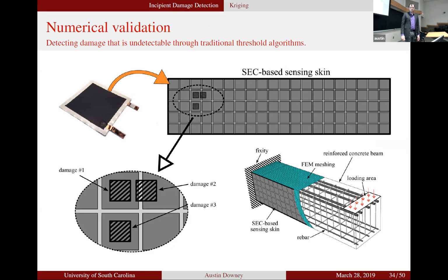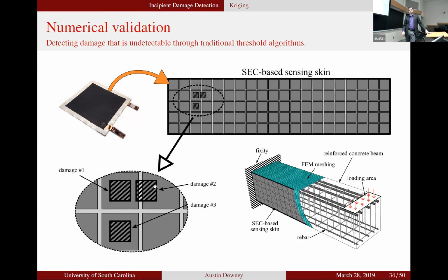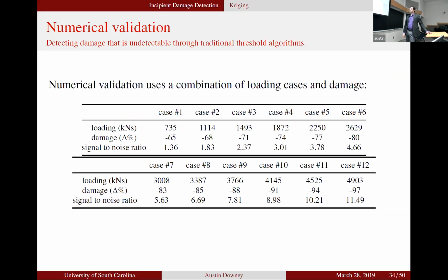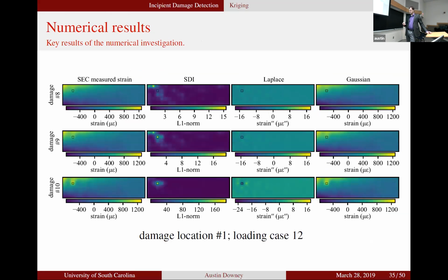Damage case 1 was selected to be in the middle of an SEC, in an area of high strain. Damage case 2 was selected to be in between 2 SECs to see how well that would work. And then damage case 3 was selected to be towards the center line of the beam where the strain would be a little bit lower. The neutral axis was a little bit farther down, but it's relatively close. So just some different test cases of increasing damage.